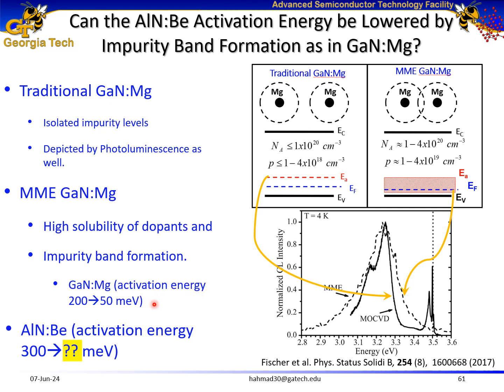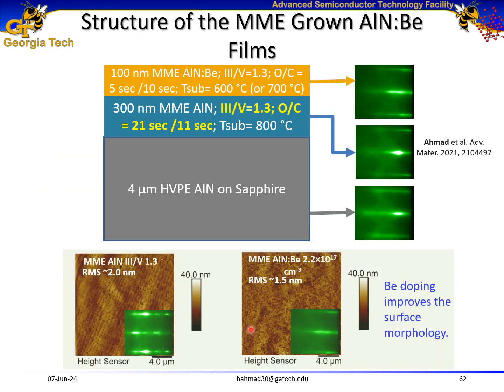So we have achieved an improvement in terms of activation energy for magnesium-doped gallium nitride, reducing it from 200 to 50 milli-electron volts as compared to literature. So now we wanted to see if we can improve the activation energy of beryllium in aluminum nitride as well. This led to my study of growing beryllium-doped aluminum nitride on top of HVPE aluminum nitride templates with buffer layers.